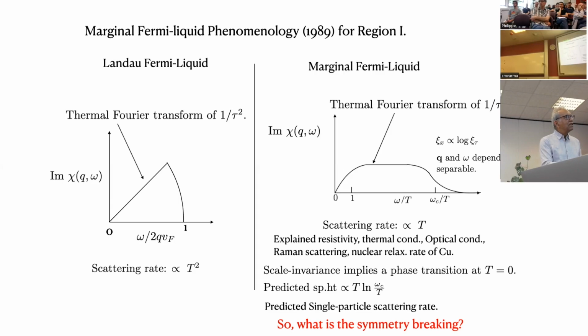Here we assumed that this object is Q independent, and it was because there are experiments done here which probe different parts of the fluctuation spectrum, different frequency range, different momentum range. For example, nuclear relaxation rate measures very low frequency, the leading omega term integrated over Q, and this thing gave us the same answer as we needed for, let's say, Raman scattering, which measures Q equal to 0 as a function of omega. Okay? So this assumption was made. But this object, you can take its real part, Kramers-Kronig, and that will be a log of omega or temperature.